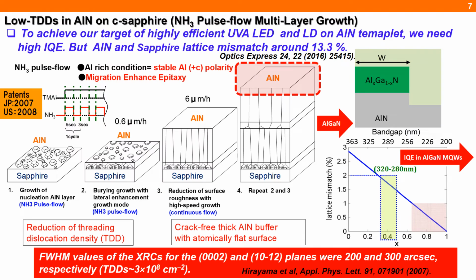Here at Riken we chose a different route of ammonia pulse flow multilayer growth to achieve our target of highly efficient LED and laser diode on an aluminum nitride template. We also need high internal quantum efficiency. In ammonia pulse flow multilayer growth, we use an aluminum source and also a pulsed ammonia source, as shown here, and we can grow a very good crystal quality aluminum nitride template on sapphire, where a threading dislocation density of 3 × 10⁸ per centimeter squared was successfully obtained.